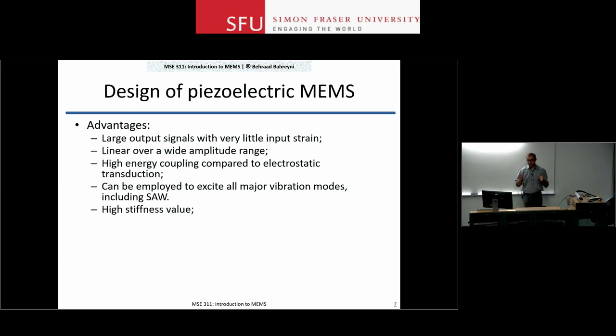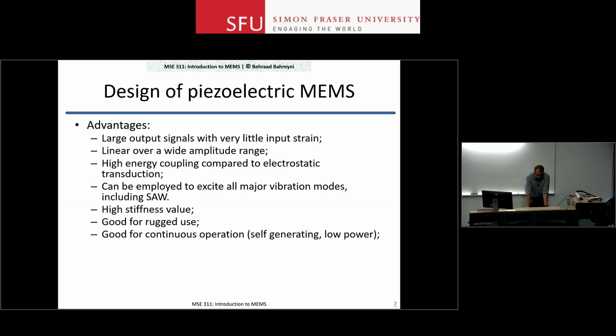You can employ and excite almost all of the major vibration modes using piezoelectric transduction, and part of it is because the transduction goes into the material and you're basically producing body forces here. Electrostatic actuation, on the other hand, applies to the surface of the device. So you really do not have access to inside the material. And once you have access to material inside the device, you can actually excite some interesting vibration modes like surface acoustic waves. The device is stiff. It is good for rugged use. You don't really have those combs that can get particles in them and damage your operating conditions. Self-generating, so you can run them continuously.